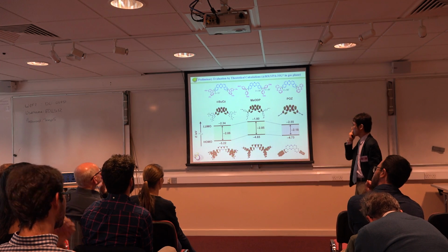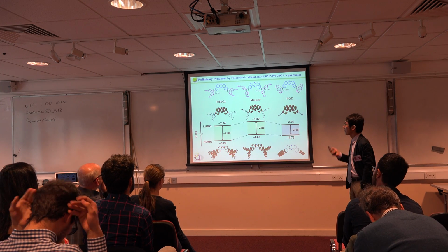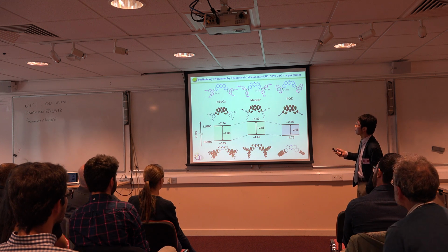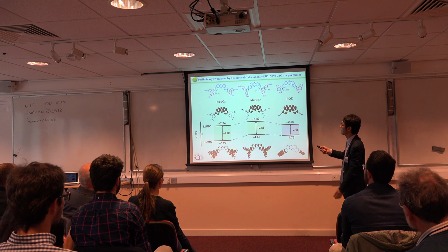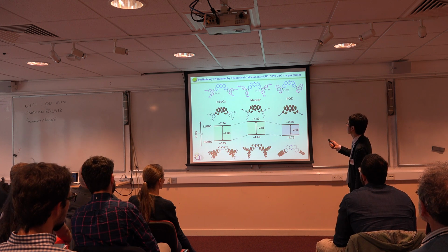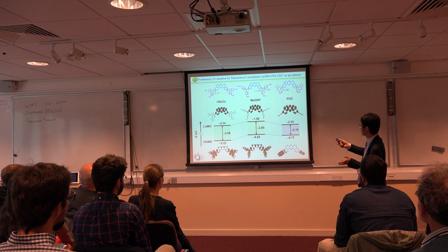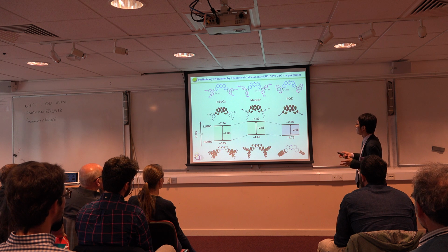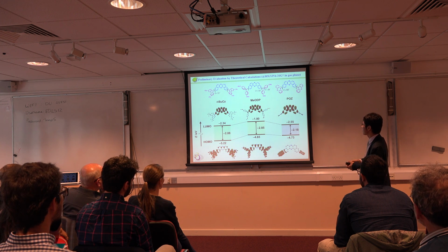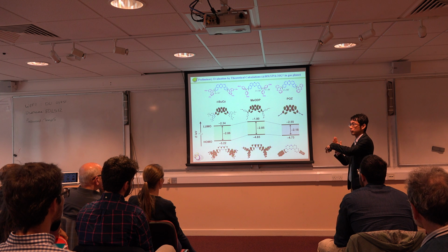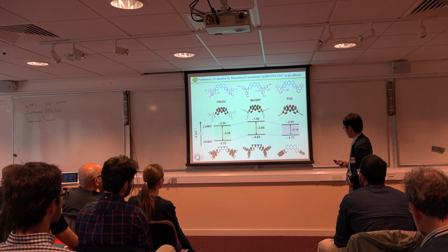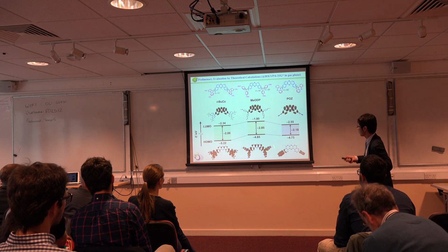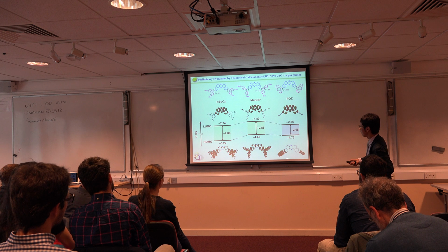Here are the DFT calculations. As you can see, depending on the donors you introduce, the twisted angles change from 33 to 83 degrees, 83 degrees especially in the phenoxazine donor case. The D-A-D systems are almost perpendicular, meaning that in that case the effective charge transfer should be very efficient.